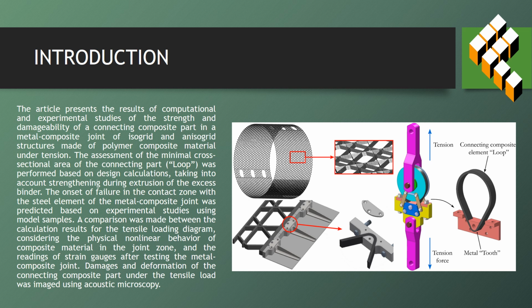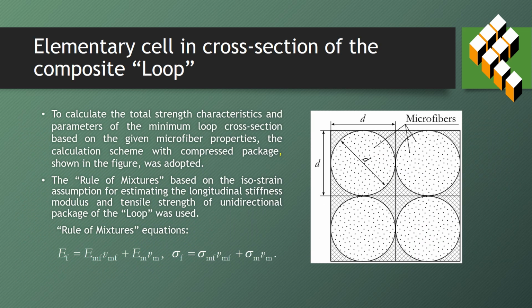The slide shows a composite structure and metal composite joint. To calculate the total strength, characteristic and parameters of the minimum loop cross-section based on the given microfiber properties, the calculation scheme with compressed package shown in the figure was adopted. The rule of mixtures based on the isostrain assumption to estimate the longitudinal stiffness modulus and tensile strength of unidirectional package of the loop was used.